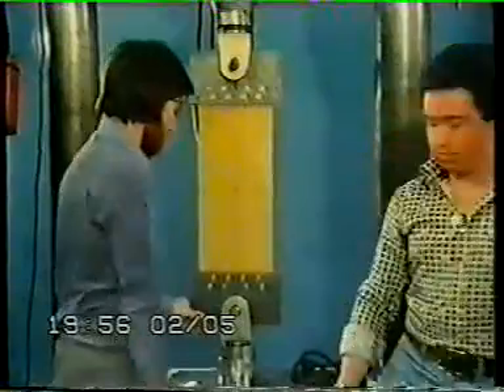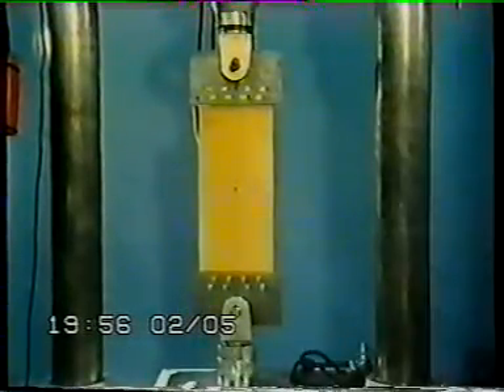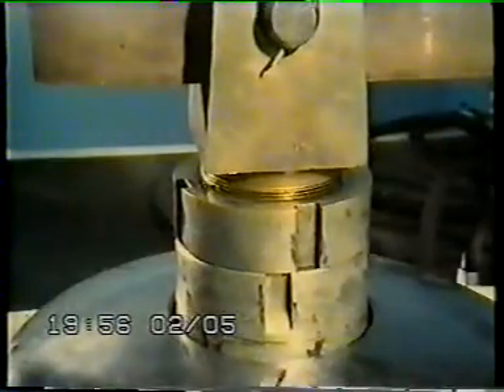Such cracks can grow from tiny flaws in the metal as the sample is fatigued. Here we are seeing the process speeded up many times. At a certain point, a critical crack length is reached. Here we can see the crack quite clearly as it nears this point. The component is now so weak that if a stress is applied equivalent to the maximum G allowed in the aircrew manual, failure could occur.